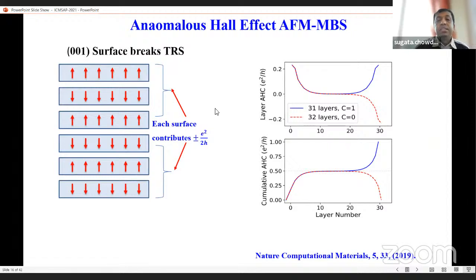You will notice that this is the structure of the ferromagnet, this manganese bismuth selenide structure. This is the spin up and spin down. And if you notice, we consider an even number of layers. When it is an even number of layers, it behaves as antiferromagnetic, and with an odd number of layers, the material is a ferromagnetic system. When we checked all our cases, we found that when it is odd, the Chern number is 1. And on the other hand, when it is even, the Chern number is 0.